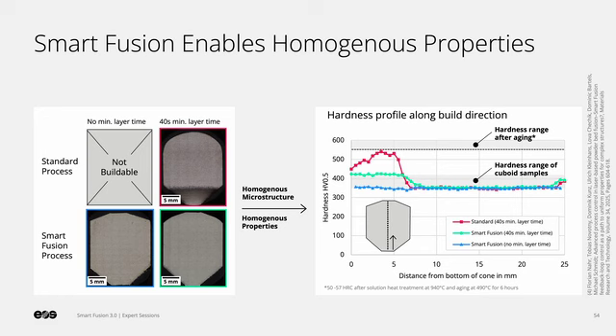In total, we have tested four combinations of minimum layer time and process control. Without Smart Fusion, we did not achieve the desired results because the part is not buildable at all or has the previously discussed microstructural changes. The different microstructure in the dark region leads to a hardness peak close to a level that is usually only achievable after aging. This supports our suggestion that precipitation is taking place during the process.